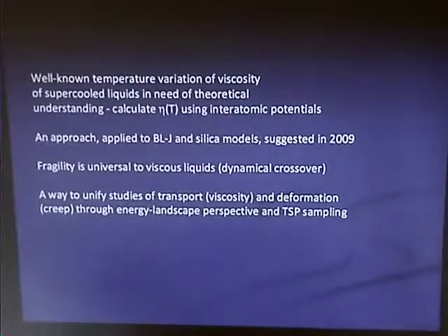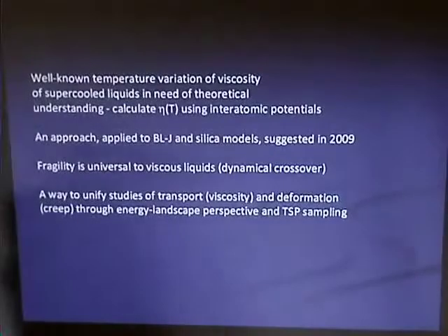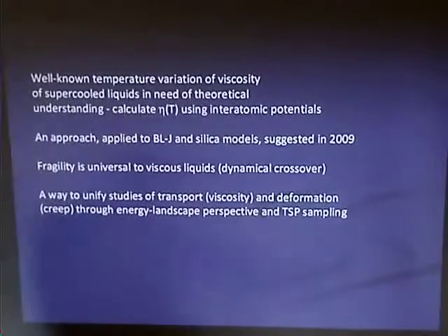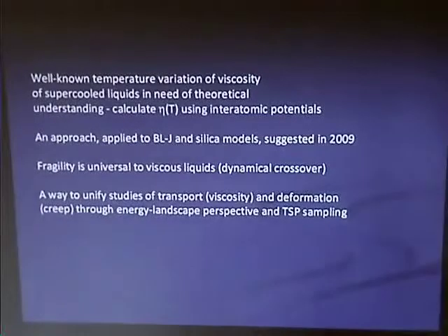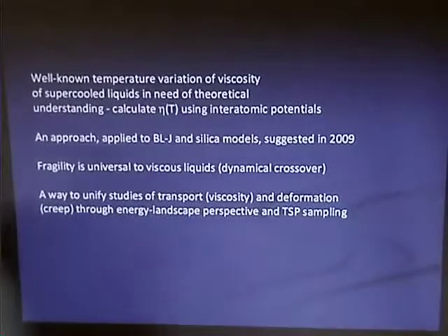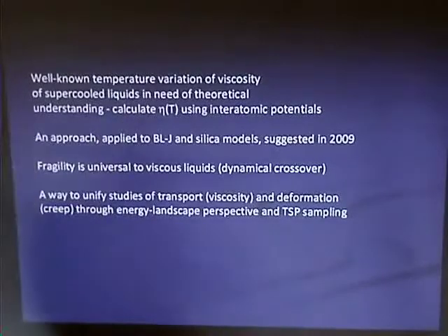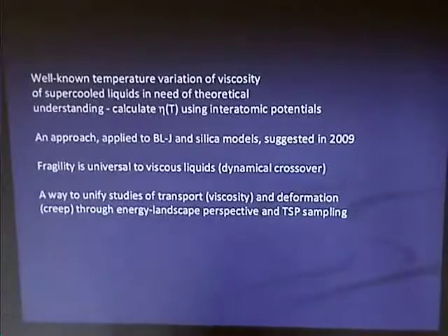I don't know. So, I claim that there's a problem that has not been fully solved, and that problem is how to calculate the viscosity of a supercool liquid using interatomic potentials and no other parameters. So it's like a prediction. You don't adjust anything, just calculate. And we have the theories to do that, linear response theory, Green-Kubo, what have you. So we can go quite a ways, but unfortunately we cannot go all the way, because when you get down to very low temperature, viscosity goes over many orders of magnitude, you run out of computing capabilities. So there is a well-known challenge there.